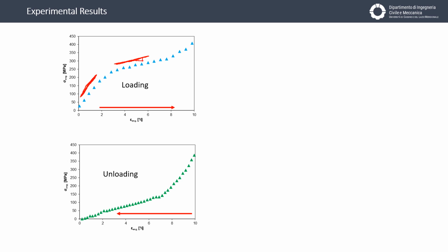It's the minimum slope that you can see in these curves. Then we have the third stage characterized by the slope of the martensite. In a loading condition, you can see the third stage is wider than the first one, and then we have a different second stage where we have a transformation of martensite in austenite. It is a reverse transformation, and then the first stage is very short here, characterized by the recovery of elastic